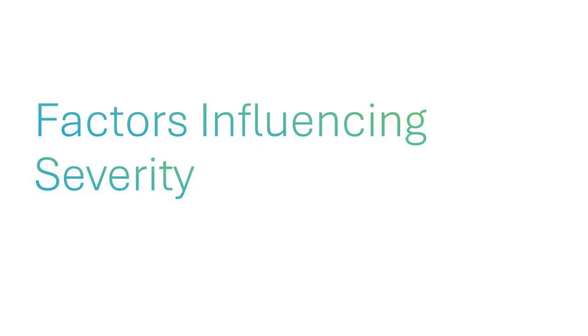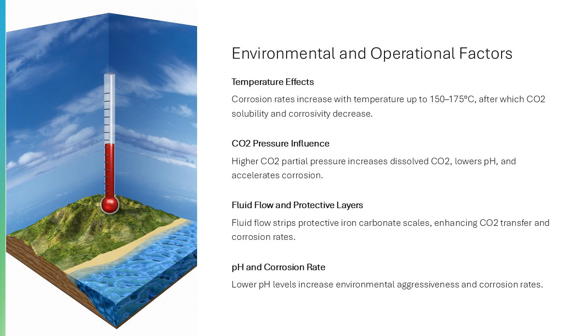Environmental and operational factors. The severity of CO2 corrosion is governed by multiple interrelated factors. Temperature plays a significant role, with corrosion rates increasing as temperature rises up to approximately 150 to 175 degrees Celsius, or 300 to 350 degrees Fahrenheit, beyond which CO2 solubility decreases, reducing corrosivity. Pressure, specifically CO2 partial pressure, is another critical factor. Higher partial pressures result in more dissolved CO2, lowering pH and accelerating corrosion. Fluid flow rate also impacts corrosion by stripping away protective layers such as iron carbonate scales and enhancing mass transfer of CO2 to the metal surface.